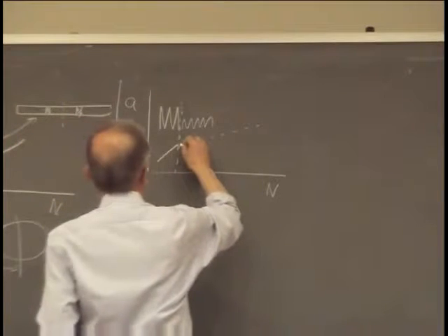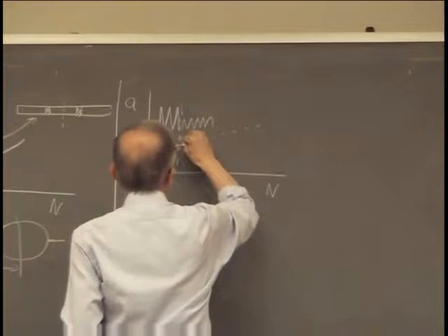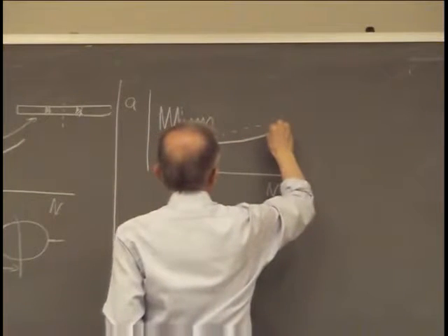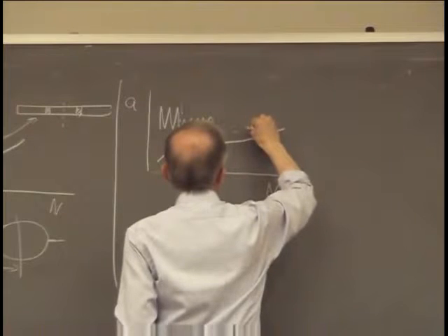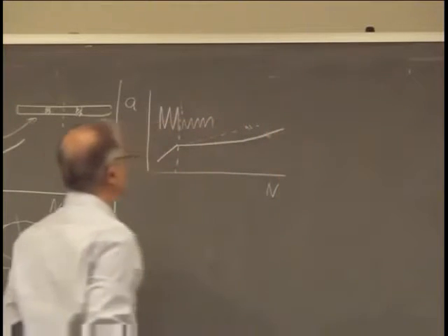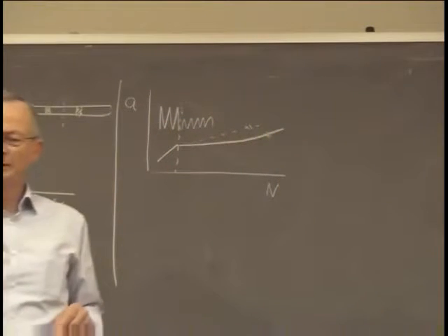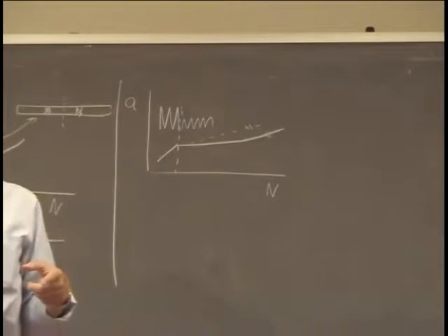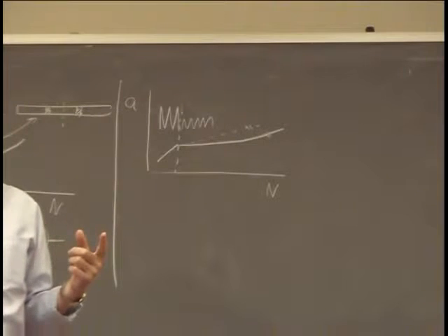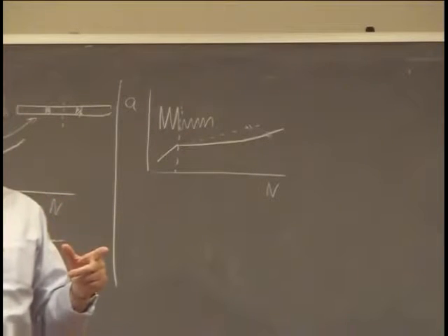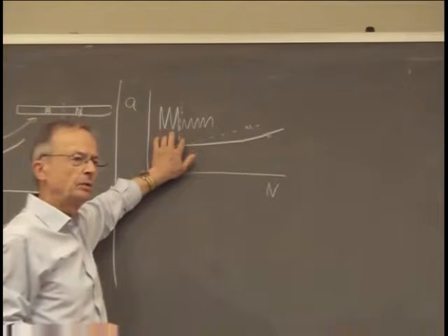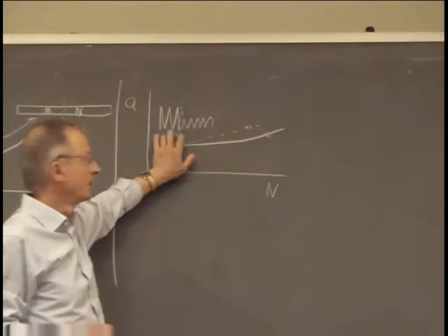We observe that at the beginning the crack is very slow, and only after a while it attains what I call the equilibrium rate. So we have a delay in crack propagation, or in other words, we gain life as we would not expect if there were no interaction between the different load cycles.